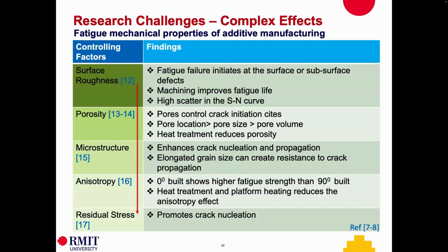Now, this again summarizes what we found so far in the literature. And we are going to explore what happens for these effects when we look at our target alloy, in this case AlSi10Mg, in the context of additive manufacturing. So that's coming up next. What we found, the controlling factors are surface roughness, porosity, microstructure, and anisotropy and residual stress. So these are what we call the key parameters of focus, the major parameters to which the fatigue life is highly sensitive. How does it affect?